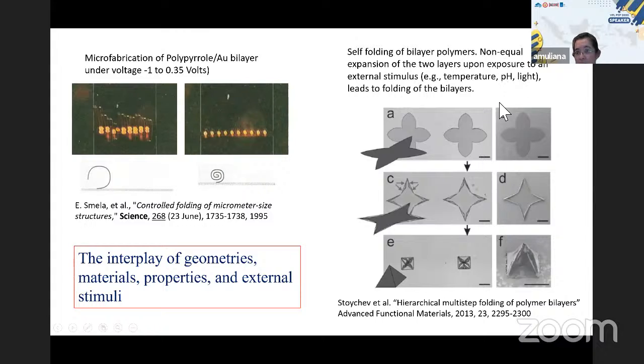Well, in the second example, this is a bilayer of two different polymers with significantly different physical properties. Through a non-mechanical stimulus, for example, you can consider temperature, pH, or moisture, you can achieve a different folding shape, right? So this example is actually the polymer folding by Stoychev. Here this folding is due to moisture absorption, because in the bilayer, they have two different layers. One is a hydrophilic polymer and the other is a non-active polymer. So the key of this is that we look at the interplay between the geometry, the material, and the properties, and of course the external stimuli, right?